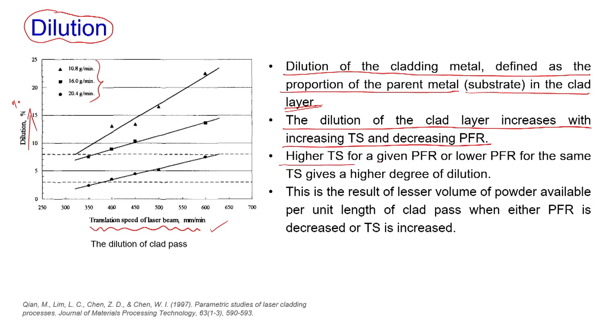So, higher TS for a given PFR, or lower PFR for the same TS, gives a high degree of dilution. If you are working at a very high TS value, a high translation speed, and if you are working with a lower PFR, so here you can see this is the lower PFR value, then you have a higher degree of dilution. The dilution is much higher in this case.